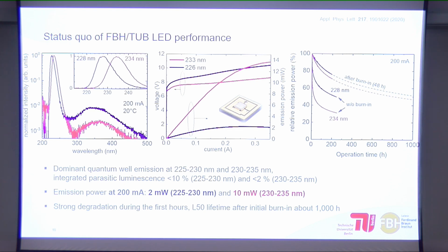What is not very encouraging initially when you look at it is the lifetime of the LEDs. So over here we have plotted the output power of the LEDs over operating time. And you see that in both cases, for the 228 nanometers as well as the 234 nanometers, within the first 50 hours of operation, you have a very drastic decrease in the output power of the LEDs. And then the decrease is slowed after the first 50 hours approximately.